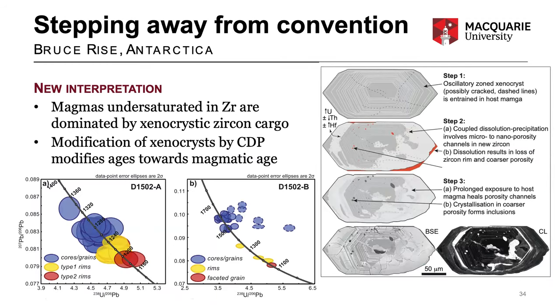So now we're starting to step away from convention. In a paper we published this year, we're putting out our new interpretation for these sort of textures, where magmas that are undersaturated with respect to zirconium are going to be dominated by xenocrystic zircon cargo. They're not going to have enough zirconium to precipitate new zircon, and the modification of the zircon xenocryst by coupled dissolution precipitation will modify the ages towards the true magmatic age. In the cartoon on the right, we've tried to show the process of progressive replacement that ends up producing quite complex zircon internal textures that include inclusion-rich areas, as seen in the backscatter and the CL images.